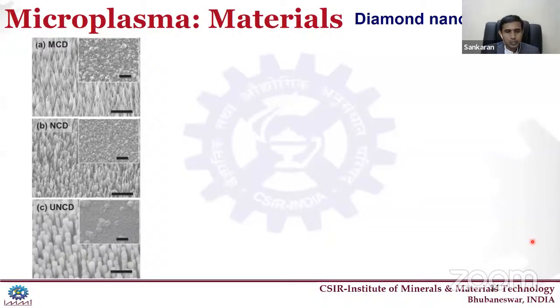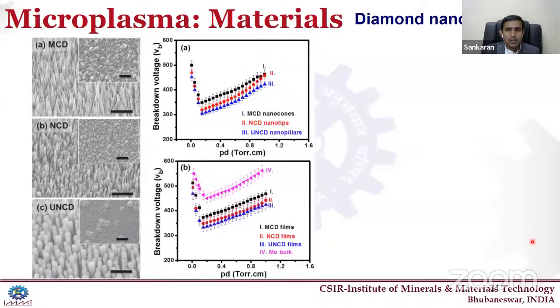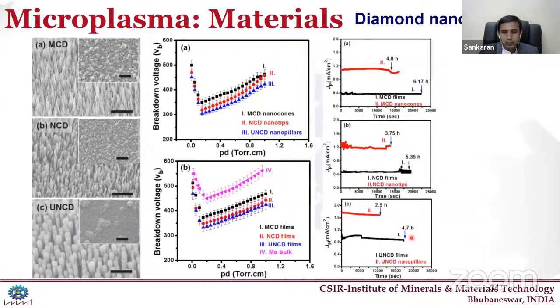And these are the nanostructures obtained from different morphologies of diamond. We also got very good plasma results in which the UNCD nanopillars or nanocones showed very good lifetime stability of more than 6 hours. So depending on the microstructure as well as the morphologies of these diamond thin films, that determines the microplasma illumination of this diamond based material. So far this is the best report, like 6 hours of continuous electron emission without any degradation of the current, which is very helpful in microplasma based illumination or microplasma based display devices.